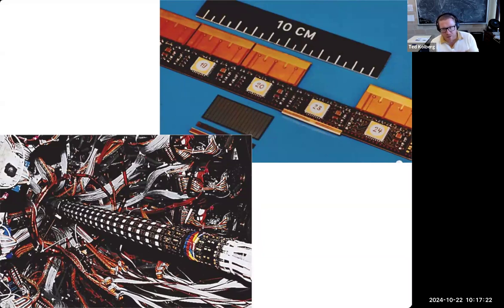There was basically a 9 millimeter radius gap between the beam pipe and the existing silicon pad detector for this new high granularity version to fit in. And 9 millimeters was just enough space for this thing with basically no dead space. So the size of the pads in this geometry is 17 by 33 millimeters with 3,072 channels. Both of these are sort of laughably coarse by modern standards, but it did represent a real pushing of the technological envelope at this time.